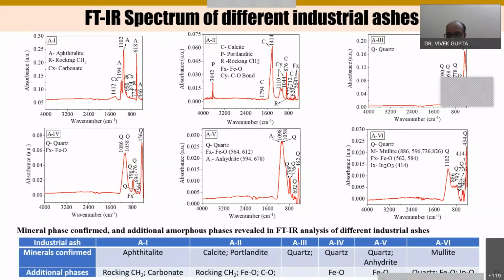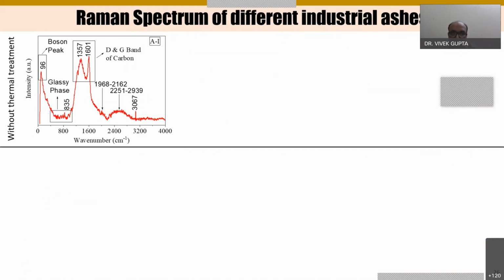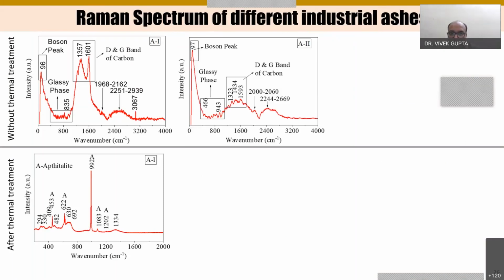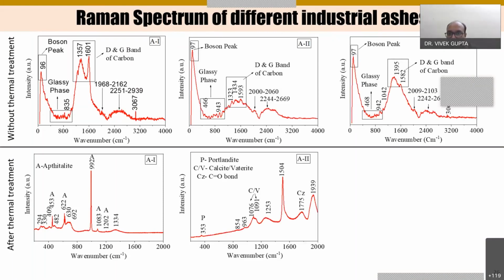Okay, so then we have carried out the Raman spectrum. In the FTIR also, we could not identify whether amorphous carbon is present or not. So we have conducted this particular Raman spectrum, and we have observed the D and G band carbon in all the ashes. And when we went through the Raman spectrum of the industrial ashes, we could identify the glassy phase of the matter present in the ash.